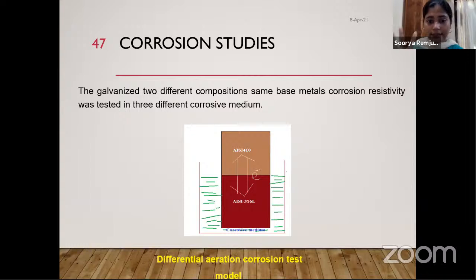Now, corrosion studies. In the differential aeration corrosion test, we kept AISI 410 on the top, and 316L at the bottom. 316L showed a much higher corrosion rate compared to AISI 410. So the top AISI 410 has less corrosion and more corrosion resistivity compared to 316L.